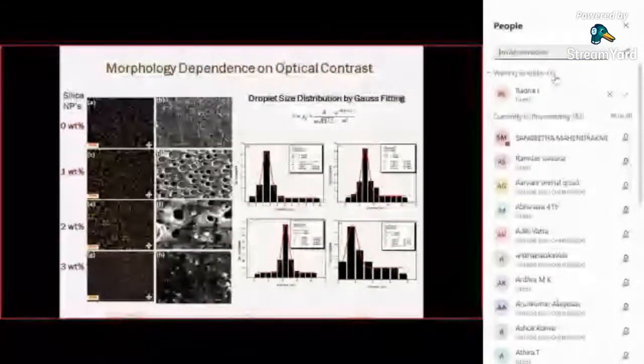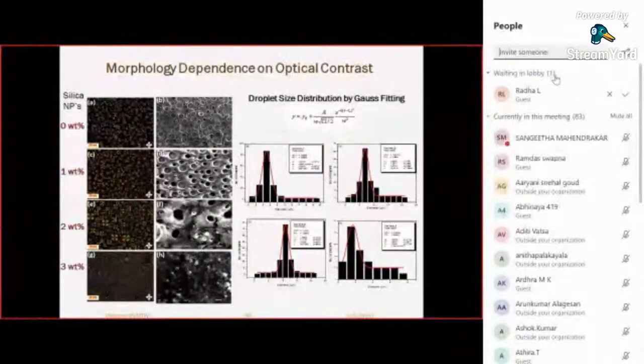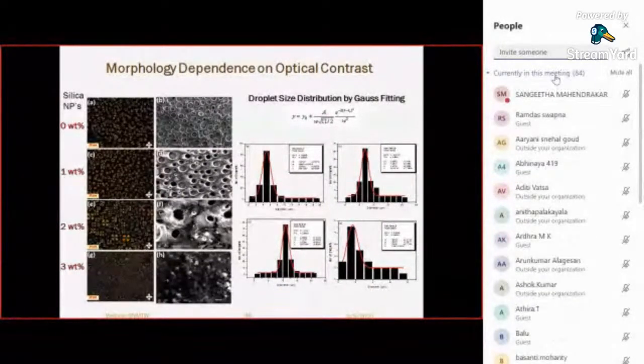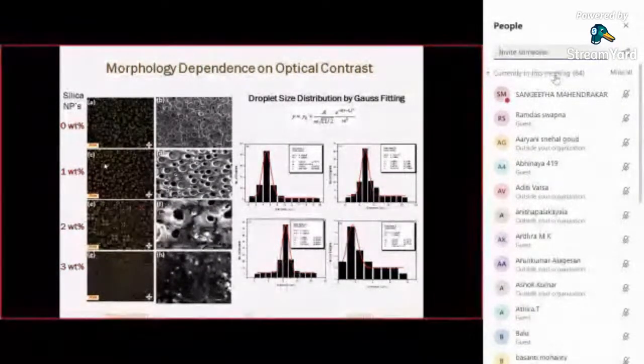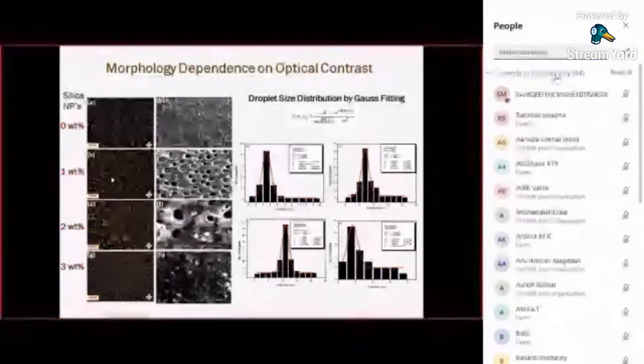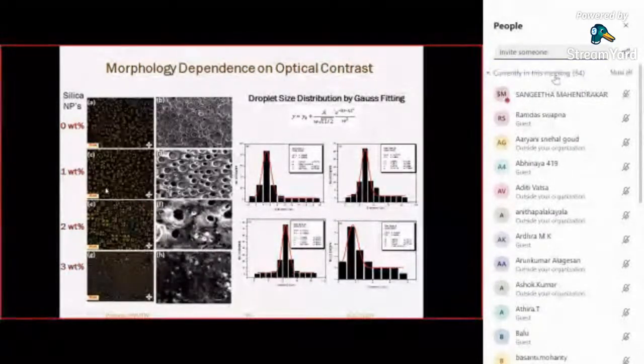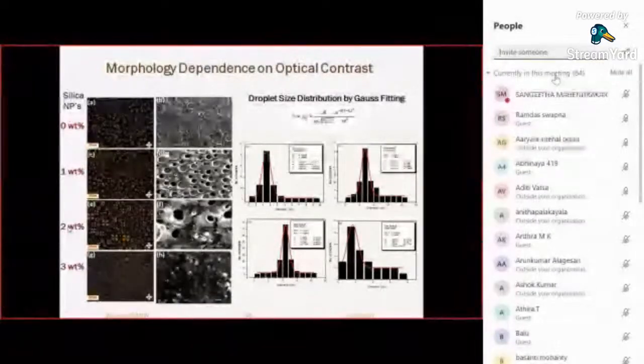These are the liquid crystals, only nematic liquid crystals, where no silica nanoparticle is there, which means this is the undoped sample. Only nematic liquid crystals and some polymers are there. After adding 1 weight percent of silica nanoparticle, I got improved droplet structures. That structure can be investigated through polarizing optical microscopy, and when the concentration is 2 weight percent, it gives a better contrast which will be applicable to displays.